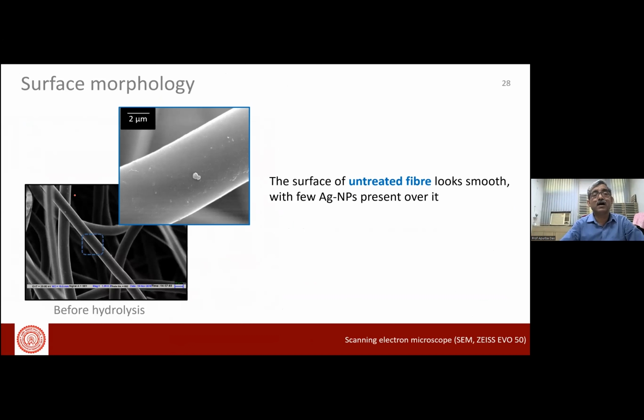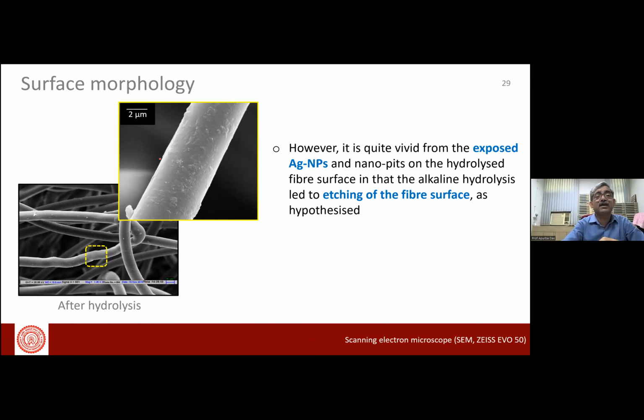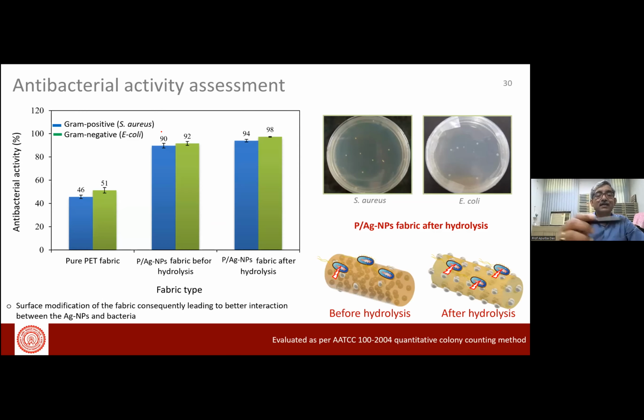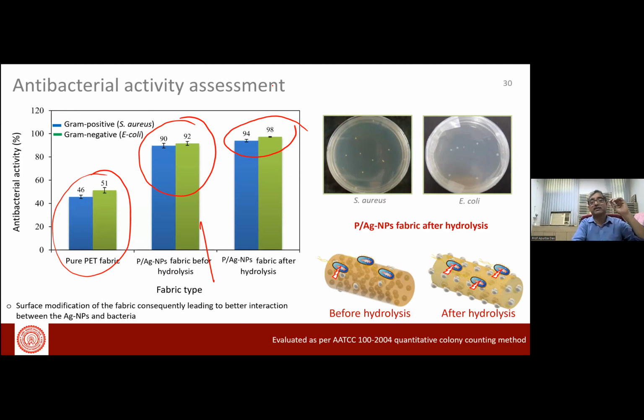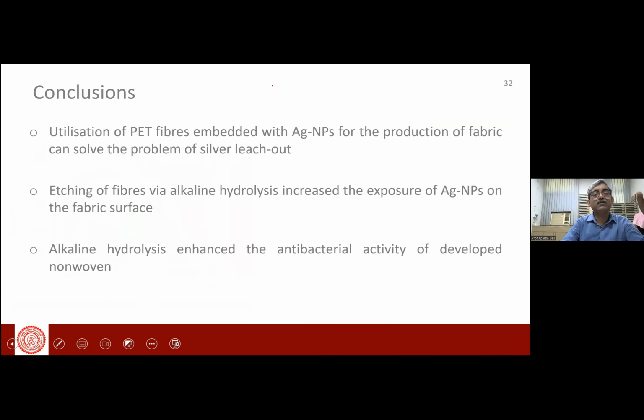Now if you see the surface morphology, this is without alkali treatment, untreated fibre. At the surface, very few nanoparticles are present. And if we see the treated sample, due to this etching out, the nanoparticles are visible at the surface, and that resulted in the improvement. This is the pure one without any silver nanoparticle, and with silver nanoparticle before the hydrolysis. After hydrolysis, you can see there is an improvement of antibacterial activity.